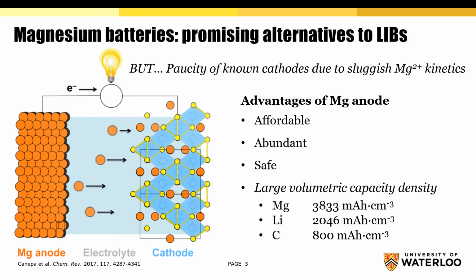However, these increased electrostatic interactions between divalent magnesium ions and their surrounding host lattice result in a severe shortage of cathode materials capable of reversibly storing magnesium ions. Overcoming these sluggish magnesium kinetics relies on the development of suitable nanomaterials that offer shortened diffusion path lengths to activate and enhance magnesium electrochemical activity.